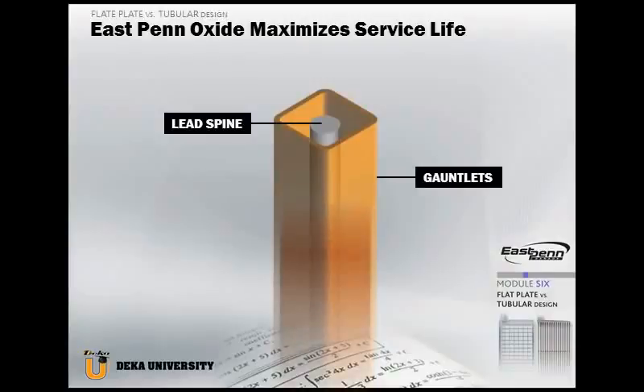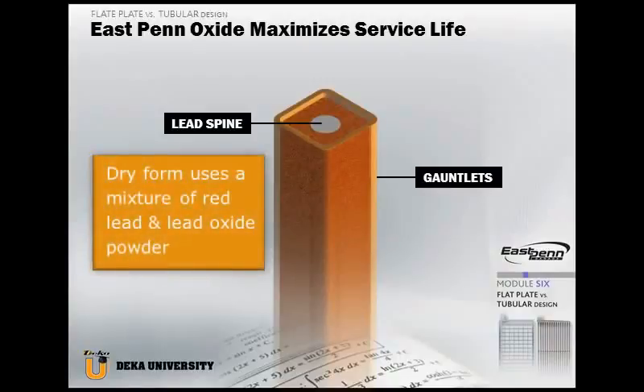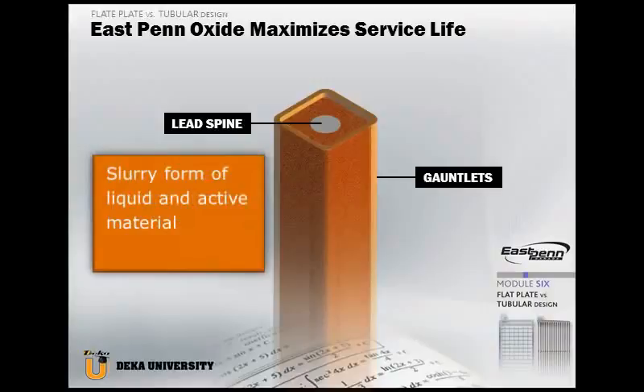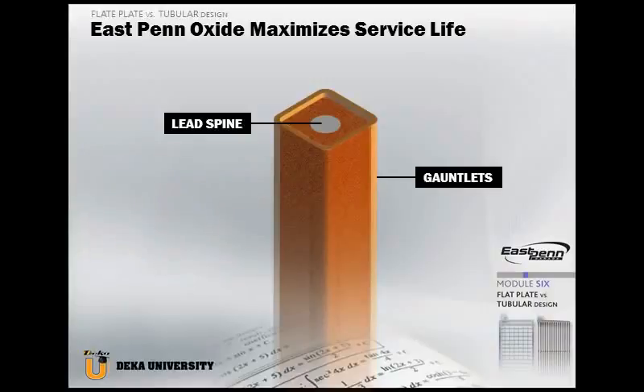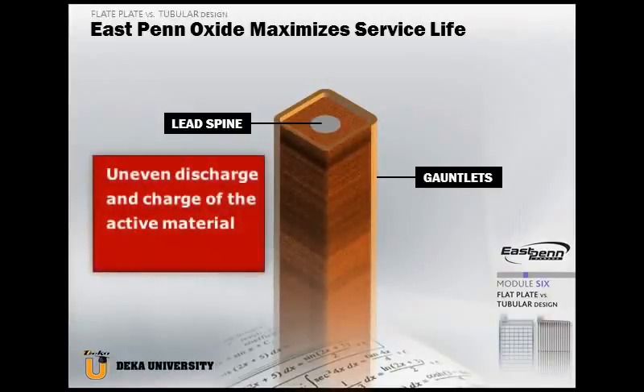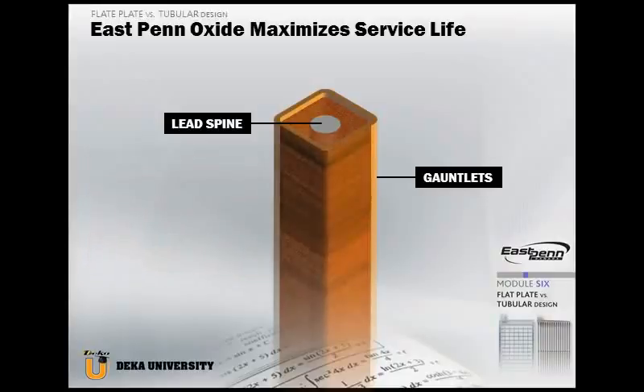For tubular designs, polyester tubes called gauntlets are filled with either dry or wet active material to create the individual tubes. The dry form uses a mixture of red lead and lead oxide powder while vibrating the plate to prevent the oxide powder mixture from clogging and assist in the flow. Alternatively, a slurry form of liquid and active material can also be used to fill the gauntlets. Both wet and dry methods can produce variation in density via the filling process, which results in an uneven discharge and charge of the active material that can lead to premature failure. In some cases, the extremely dense material can split the retaining gauntlet, resulting in severe shedding and major capacity loss.